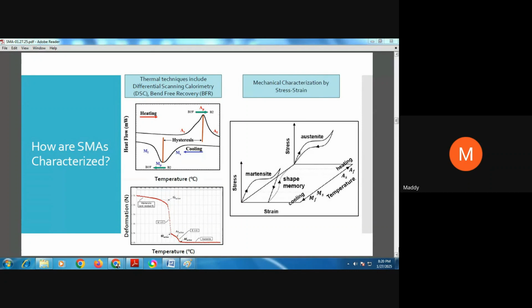On the right-hand side is your typical stress-strain curve. If we start with austenite, which is on the back end of the chart, you will see that when you apply stress, there is a forward transformation from austenite to martensite, and then when you release the stress, you revert back to austenite, which is the reverse transformation. So you have upper and lower plateaus. These are very, very important. And when the starting phase is martensite and you apply stress, the profile that you will get is what you see here. There is also a plateau here, but this is not stress-induced transformation. This is what is called the detwinning of martensite. The martensite that is twinned, on application of stress, gets detwinned. That's why you're seeing that strain that is self-accommodating.